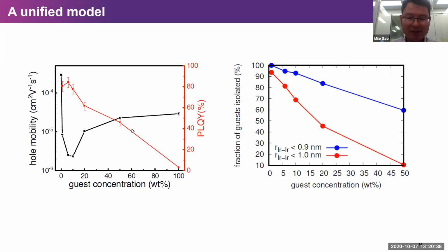And now let's turn to the photophysical properties. Remember that we said they follow different regimes. The PLQYs, for example, from 1 to 10 weight%, are high and they are all in the 80 to 85% range. But when the concentration increases to 20%, it decreases.